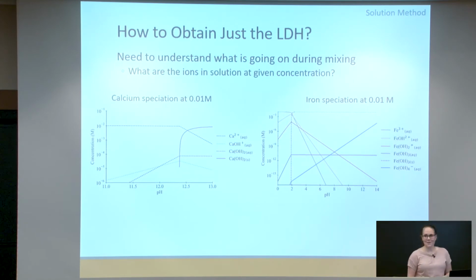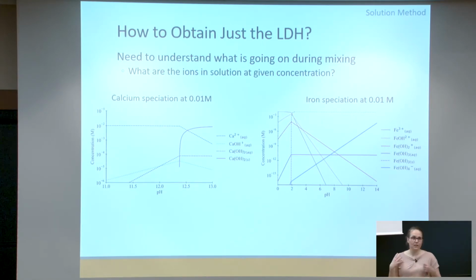I don't have time to go through the details, but it comes down to a lot of chemistry. Essentially, we need to understand what the aqueous species in solution are as a function of pH, because they are the things that come together to form the solid. We want to know about those, and we also want to know if there are going to be any solids that form as well. For calcium over here, this solid line is indicative of solid calcium hydroxide, that Portlandite. So we want to stay below the pH at which that forms.